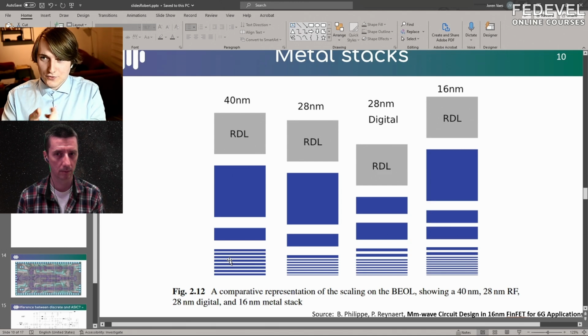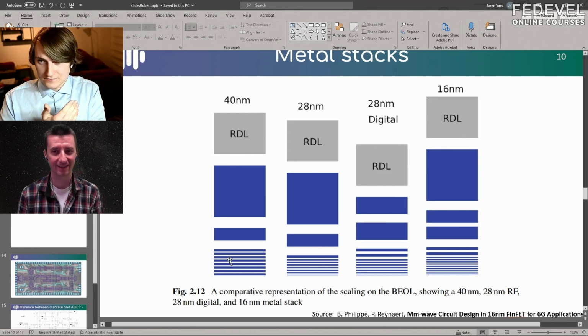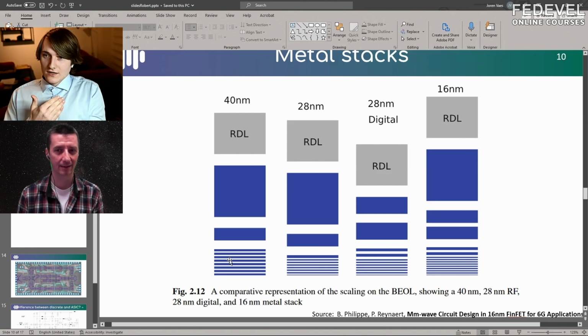And before you know it, if your wire is too thin for the amount of current that's going through, it might actually bump so many atoms aside that you get a gap in your metal. And so the connection that was made, you have an open circuit. Open circuit, sorry, yes. I have an open circuit.